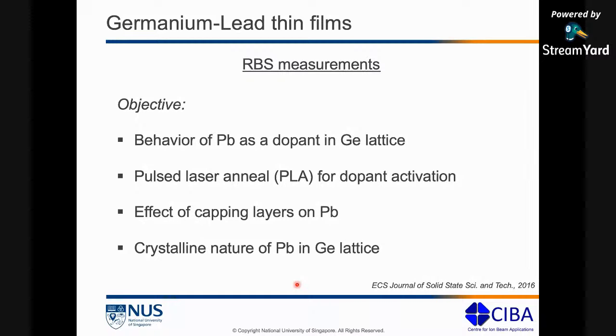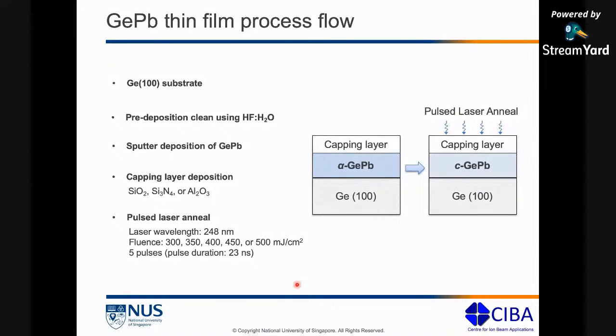And this was the thin film process flow that was followed in making these samples. So starting from a germanium substrate, these were sputter deposited germanium lead films. As deposited, they came as alpha germanium lead, and then after the pulsed laser annealing step, there was a phase change to C germanium lead. The capping layers that we used were silicon oxide, silicon nitride, and aluminum oxide. And then these are the pulse laser parameters that were used to activate the lead within the germanium.